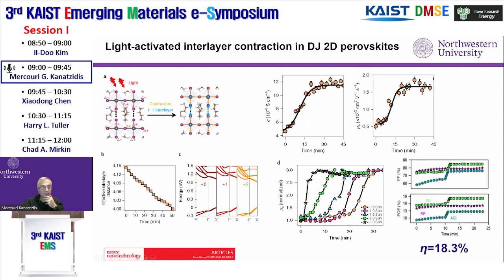And then the electron goes into the conduction band, which is based on the lead. The hole, because these are so close, partially oxidizes the terminal iodide and makes it shorter. And parts of the holes localize here. It's like making an oxidative coupling, trying to make an iodine bond across the layers, and that contracts the lattice along the stacking direction. At the same time, as shown by the calculations, now you have some path for holes to cross from one layer to the next, as the valence band becomes a little bit broader. And that can account for the higher mobility. And the devices then, after some illumination, suddenly after 10 minutes of illumination, jump in efficiency from something like 16% to 18%, which is quite interesting.